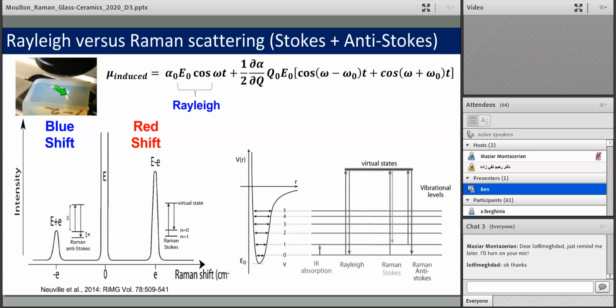When scattering happens in this process, you can have 3 different situations. So the photon comes in, it hits the vibrational ground state here. They interact and create what's called a virtual state that happens on the order of picoseconds. And this, instantaneously, or at least as experimentally instantaneous, decays and releases a photon that scatters out of the material. If these photons interact with the phonons and scatter at the same frequency that they came in at, we call this Rayleigh scattering. And so there's no change in energy. Whatever the energy is in here, we call zero, or E naught. If there's no change in frequency, we call this Rayleigh scattering, and this front term in the equation describes Rayleigh scattering.